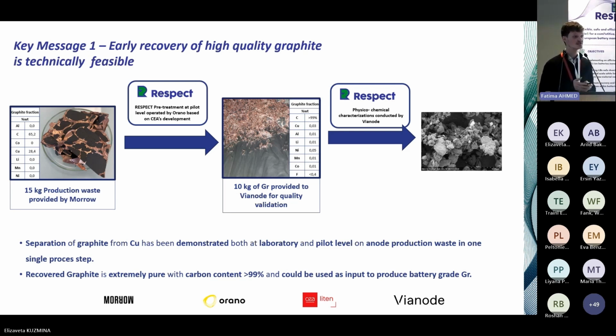So we received 15 kilos of this fraction. You have a rough idea of the material composition, so around 65% of carbon content and 28% of copper from the copper foil. We have applied the process developed in the RESPECT project, and we managed to separate a really high quality of graphite with this single process step separation with more than 99% of graphite content.